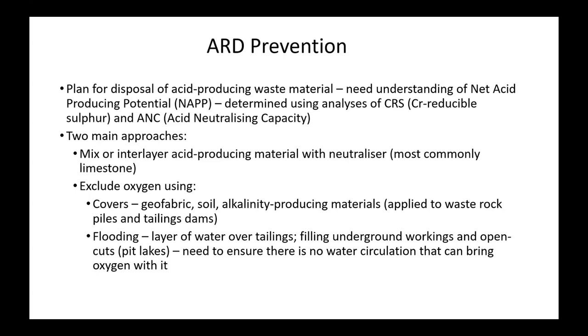So there's about 21% oxygen in the air, but it's actually a surprisingly insoluble gas. So the amount of oxygen in surface water in contact with the air and in equilibrium with it is only 8 to 10 ppm. So if you can flood it, your waste rock piles or your tailings dam, and keep the water fairly stagnant, that amount of oxygen will be used up quite quickly, and then no more oxidation will occur. So putting a layer of water over tailings or filling the underground workings or open cuts with lakes can be quite effective. However, you've got to ensure there's no water circulation, because if the water's circulating through it, it's bringing in new oxygen all the time, and that will continue the oxidation and acid generating process.